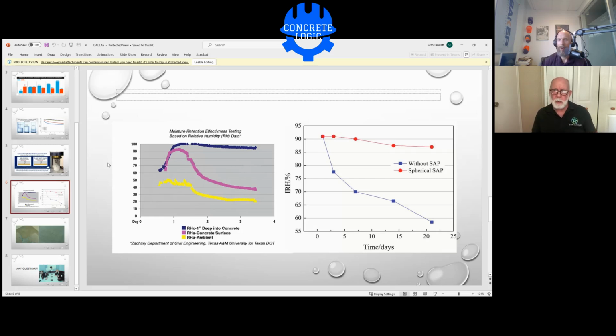The technology is all over the place, and we can more than double the durability of concrete virtually overnight if we just start accepting the curing practices. Because the two tenets of durable concrete are water-cement ratio and curing. If they're both done ideally, you get really durable concrete. And we're not doing that. We're still following 100-year-old technology of concrete that doesn't exist any longer.